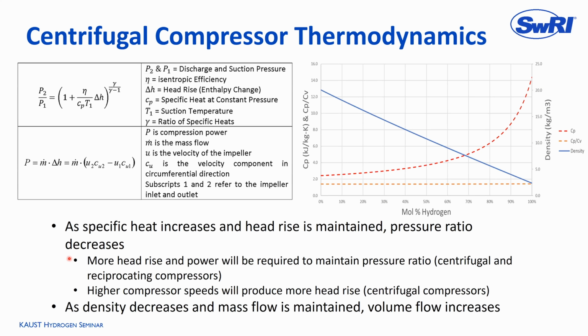Okay, I don't like to go over too many equations, but I'll throw a couple at you. In terms of compression, these are the fundamental thermodynamic equations that apply. I'll start on the right with some of the properties of hydrogen. So I'm plotting the specific heat in red dashes, the specific heat ratio in orange dashes, and then the density in a blue line. And that's as a function of hydrogen blended into natural gas from 0% hydrogen to 100% hydrogen. So as we add hydrogen to a natural gas mixture, the density actually goes way down. Hydrogen's a small molecule. And the specific heat goes way up, order of magnitude. And the specific heat ratio stays about the same.